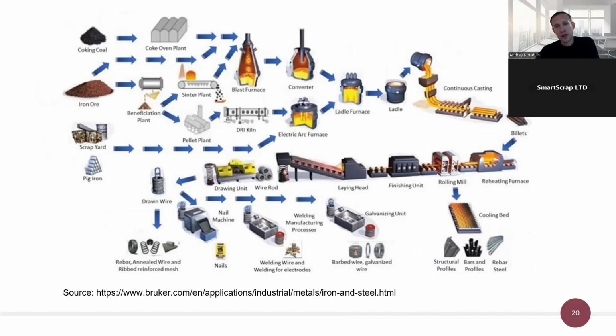After converter and electric arc furnace, liquid steel goes to ladle furnace. The purpose of ladle furnace is to adjust steel to a correct chemical composition. So in ladle furnace, we reduce harmful elements like sulfur, copper, and phosphorus, and increase useful elements like nickel, chromium, molybdenum, or others. Then liquid steel goes to continuous casting machine, and we have billets. The billets go to rolling mill, and in rolling mill, steel mill produces long products like sheet, rebars, different profiles, bars, wire rods, etc.